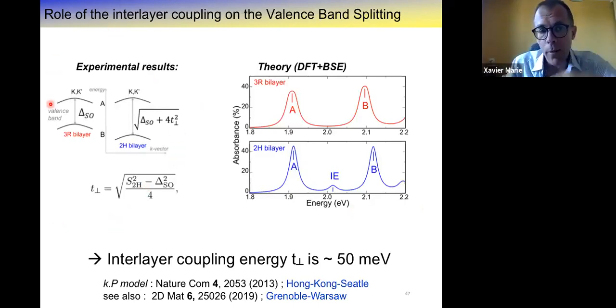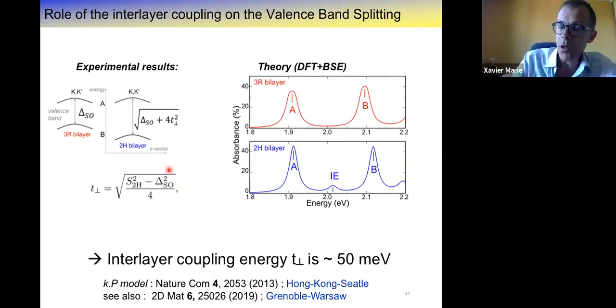And you can quantify this interlayer coupling with a very basic k·p model at the symmetry point K. From this, you can extract the energy difference of the splitting for 3R. And with this very simple approach, comparing with the splitting for 2H, you can quantify a little bit the interlayer coupling between your MoS2 monolayers. So it's a way, in this very simple system, to get information on the coupling mechanism.